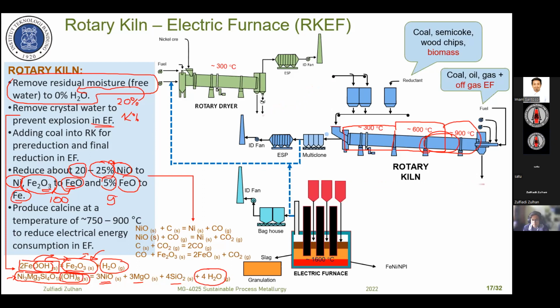95% is still in the form of oxide, in the form of wustite, and around 5% or even less than 5%, it depends on the condition in the rotary kiln, is in the form of metallic iron. And last one here, we discharge the calcine.